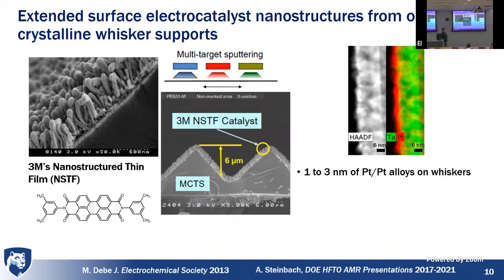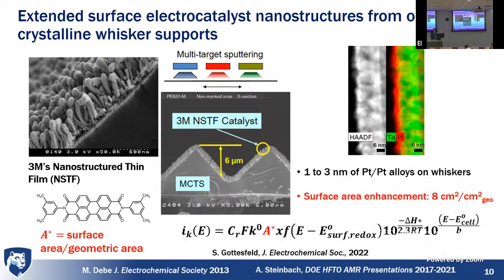You might put down, like in this case, a layer of tantalum followed by a layer of platinum. You could co-sputter different metals together. So if you alloy with cobalt and nickel, you can get higher mass activities, but sometimes cobalt and nickel have degradation concerns. And then if we look at a fundamental equation, like this kinetic current at a given potential, we want to get as much current density as possible at, say, 0.9 volts. I don't want you to look at all of the parameters in this equation, but I want you to see this A, which corresponds to the surface area. This is the amount of surface area per geometric area.